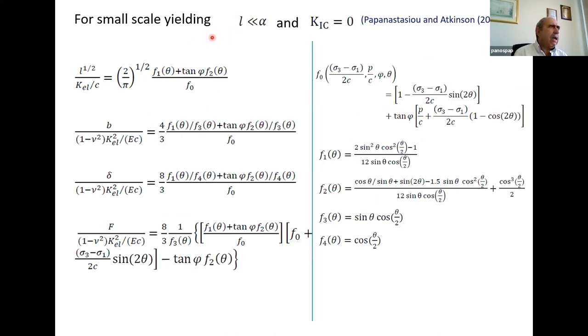particular cases, like small scale yielding, when the plastic zones are much smaller than the fracture length and the fracture toughness is zero, it's possible to derive the equations in dimensionless form, as you can see here, for the length of the dislocation and the crack opening displacement. B is the strength of the dislocation, delta is the crack opening displacement, and F is the force, which is a good measure of energy to propagate a fracture.